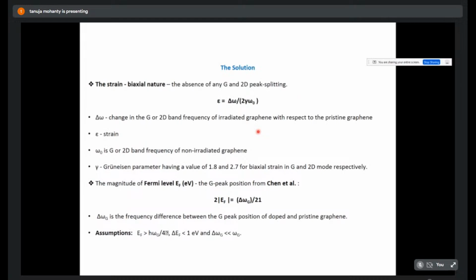So that strain can change the properties not only mechanical, also optical, as you are seeing in the Raman. So Raman will say whether the strain is induced in it or not. Particularly here, the strain is not that much, because the peak splitting is not that much. And we have also seen the magnitude of the Fermi level, EF, that is the graphene Fermi level, which is related to the G peak position like this, that we can find at 2EF equal to the variation delta omega G by 21. So this delta omega G is the frequency of the G peak position of doped and pristine graphene.